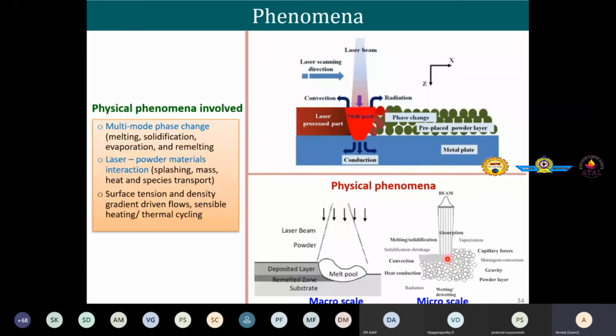So here I summarize the physical phenomena involved: multi-mode phase change, starting from melting, solidification, evaporation, and remelting. Then laser-powder material interaction. During this interaction, mass, heat, and species transport. And then in the melt pool, surface tension and density gradient driven flows. And then when you move to the next layers and next tracks, you have repeated thermal cycling phenomena. So you understand now that the physical phenomena involved are quite intricate.